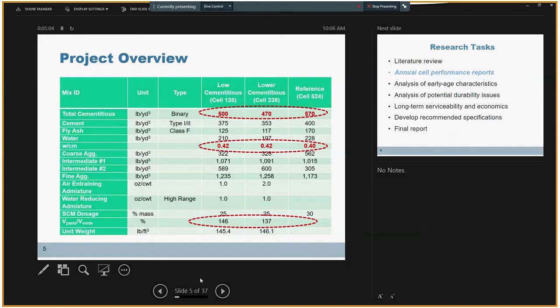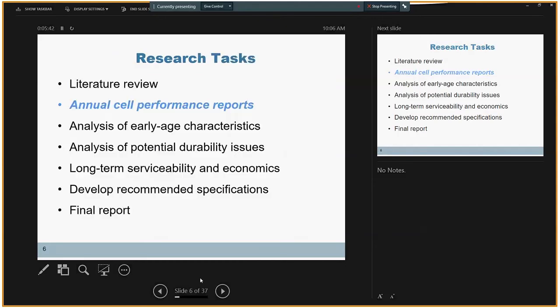Here is a summary of the concrete mix designs. Cells with low and lower cementitious material content, 500 and 470 pounds, had a 0.42 water to cementitious materials ratio, and we had 25% by mass of class F fly ash for the concrete used in these two cells. The reference concrete was cast with 570 pounds of cementitious material, a 0.4 water cement ratio, and 30% by mass of the same type of fly ash.